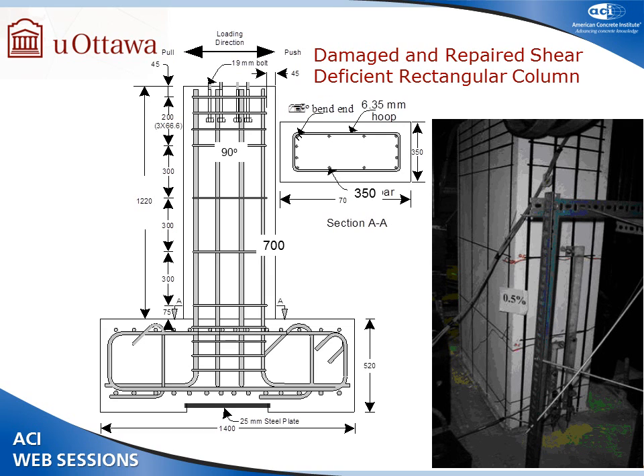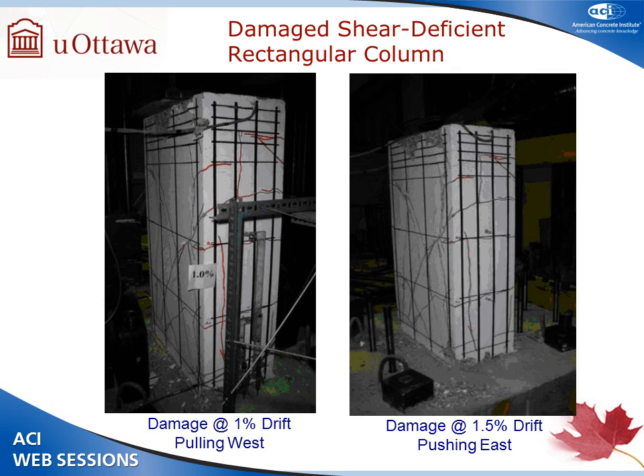Now, then we damaged columns and repaired them to see if it can be used as rapid repair after an earthquake. And we intentionally avoided doing anything else, but we just wanted to simply try to laterally squeeze these columns, having developed diagonal cracks. And initial phase involved shear cracking, and I'd like to show you those. I also had a circular column, but we were being greedy. I wanted to get 1.5% drift. It disintegrated. They failed in shear very, very in a brittle manner.